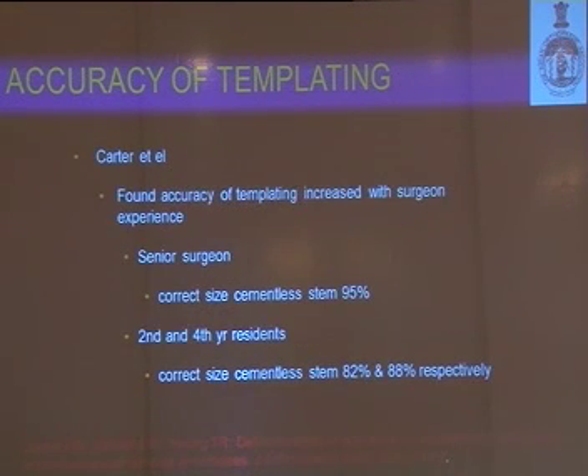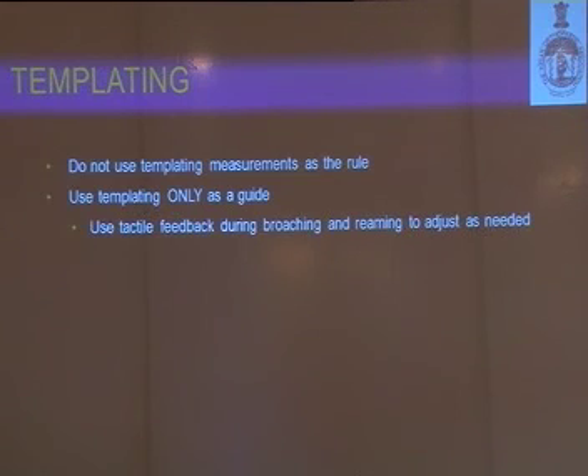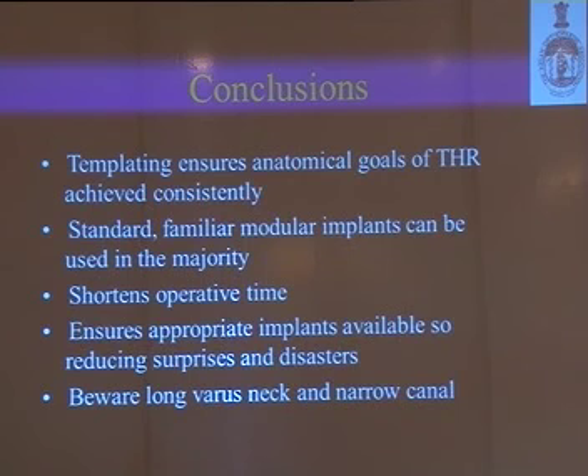Similar results were reported by Carter et al., with the correct size of cementless stems achieved in almost 82% of the patients done by residents. So I think we should not use templating measurements as a rule, but only as a guide. You still have to base your surgical approach on tactile feedback, using broaching and reaming to adjust as needed.